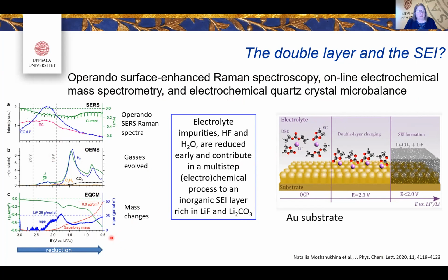not really alloying the lithium with gold, because that takes place at 0.3 volts. We didn't go that far down. But you can see here that you do form a lot of gases, hydrogen and carbon dioxide, some ethylene as well. And you can see that you have mass changes in this, indicated by EQCM. And we see that the electrolyte impurities you have, like HF and water, are reduced early, and they contribute in a multi-step electrochemical process to an inorganic SEI layer rich in lithium fluoride and lithium carbonate.